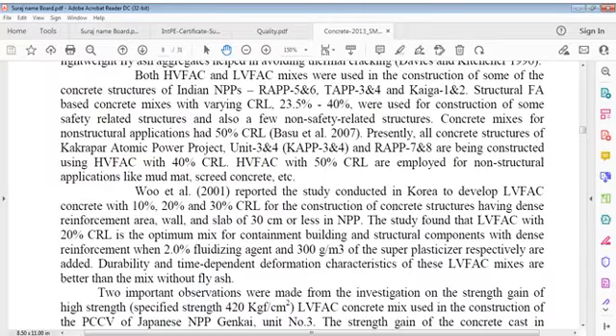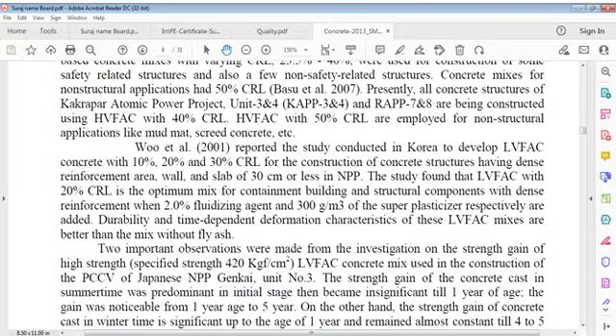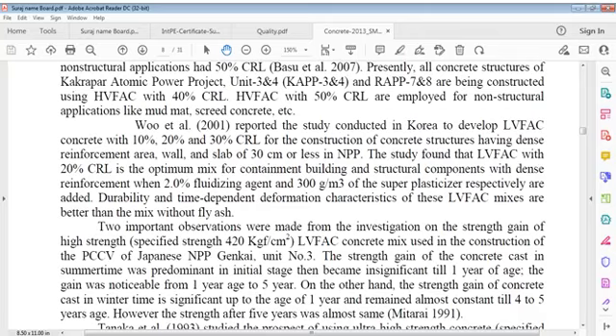It is reported that a study conducted in Korea developed LVFAC concrete with 10%, 20% and 30% CRL for construction of concrete structures. 20% CRL is the optimum mix for containment building and structural components with dense reinforcement, when 2% fluidizing agent and 300 grams per cubic meter of superplasticizer respectively are added.